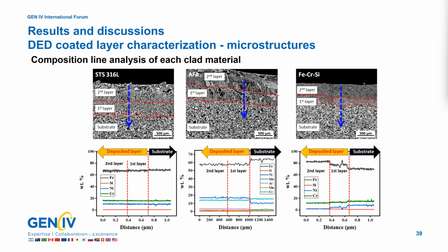The composition line analysis results for each material under the selected conditions are as follows. STS316L and AFA showed almost the same composition throughout the layers. For iron chrome silicon, the first layer showed an irregular composition distribution, while the second layer showed a relatively constant composition.